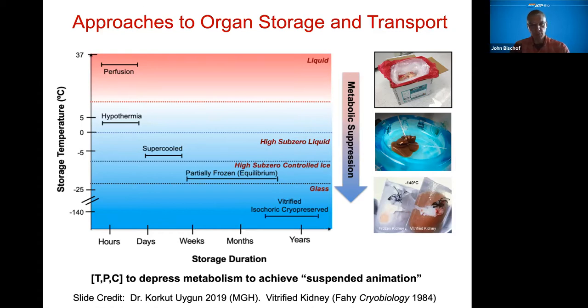And what my group is doing is we're actually trying to be also in the glass. And there's also a group at Berkeley working on isochoric, which is using pressure manipulation so that the ice crystal, which of course has a different density than the water, can never actually form. So if you're in a high enough pressure situation, you can't actually change volume. So you basically stay in a liquid state, even though you've dropped the temperature way below the liquidus.